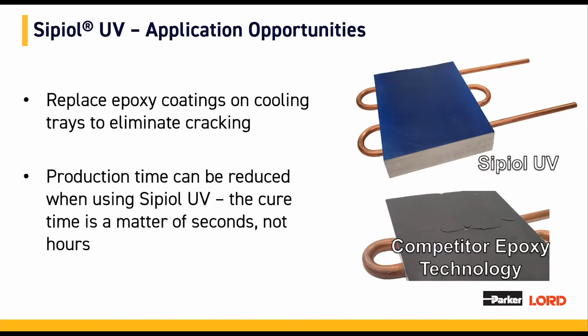One major application area is on cooling trays. When used on cooling trays, it eliminates cracking as seen with some epoxies. Epoxies can be brittle and can crack with rapid temperature changes, shrinkage during cure, or when exposed to environmental or mechanical stresses during use. In the images on the right, you can see a mock cooling tray coated with Sipiol UV and a mock cooling tray coated with a competitor's epoxy. Note the cracking in the black epoxy coating that was seen after temperature cycling.